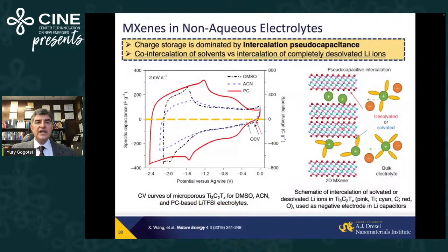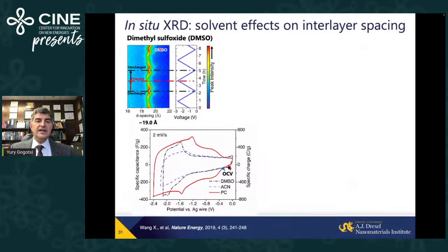Now, if we take non-aqueous lithium electrolytes, lithium TFSI, for example, and look not at different ions but at different solvents, again, you will see drastic differences in the shape of cyclic voltammograms. And if you take lithium TFSI in DMSO, a solvent which was used in the first generation of lithium-ion batteries, you will see that when we charge and discharge it, X-ray diffraction shows variations, expansion and contraction of the lattice, and a large interlayer spacing. With a layer of Ti3C2 being less than 1 nanometer, we have about 9 angstroms, almost 1 nanometer, of electrolyte between the layers.